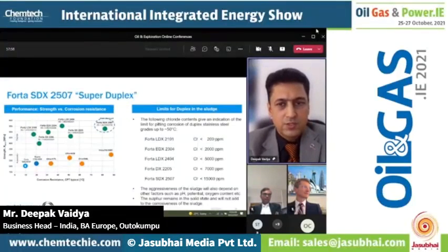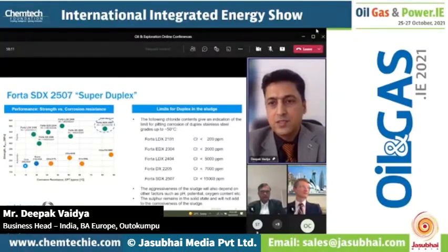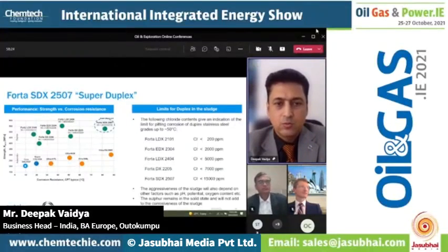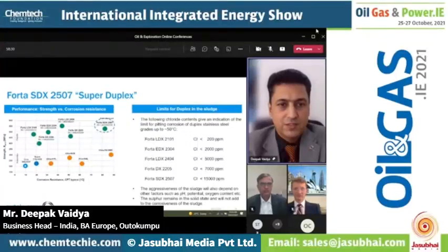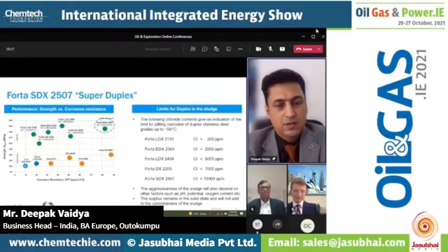What is 2507? On the right side, you can see when we are using different grades of stainless steel in chloride-containing environments in the coastal areas, the grade is selected basically on the ppm. And surely in India, where the tank farms are situated, the ppm of the water is too high, and the temperature levels we are talking about are not ambient like Europe, 20 or 22 degrees centigrade, but temperatures like 45 degrees centigrade. So 2507, we have tested 2205 also, but we found that 2507 actually provided the life expectancy that was planned.